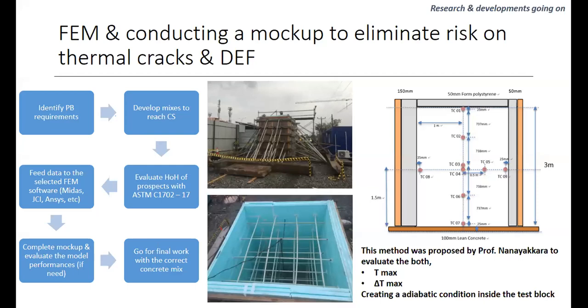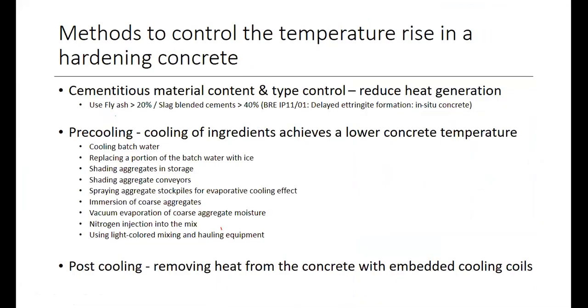So if we can do such modeling with the new engineering approach, we need only one mock-up, if required, to identify the heat generation and other parameters. This method was developed; usually, the former specification requested two different mock-ups to identify the core temperature and the surface temperature separately. But Professor Nanayakkara has developed that method. With a single mock-up test, we can get the core details to identify the possible highest temperature and the highest temperature gradient. And with different kinds of methods, we can reduce the risk of heat of hydration.